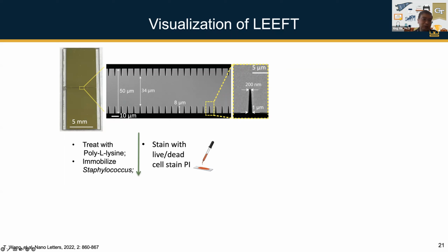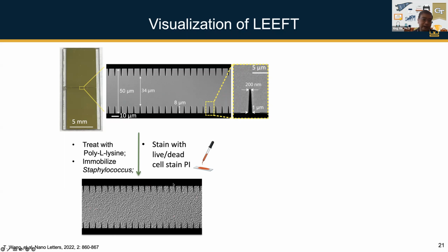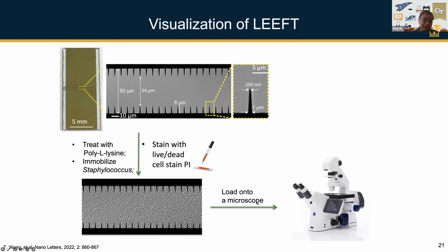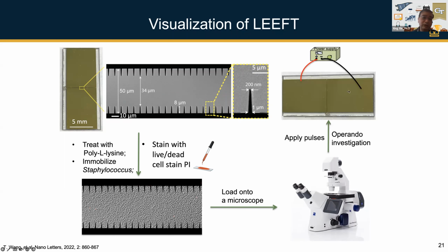and then we coat the surface with model bacteria, Staphylococcus, with staining. The idea is that we want to do the LEEFT treatment process on this chip. At the same time, we put it under the microscope while we apply the electric field, so we can visualize this LEEFT process and do operando, in situ investigation of this process.